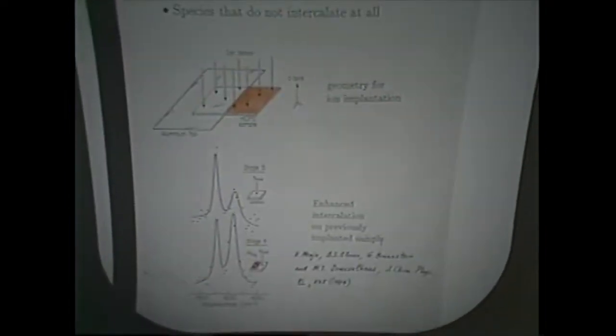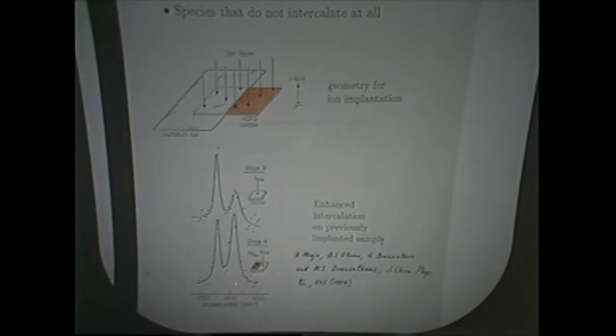So we have a control sample. Oh, well, I guess this is the whole thing. So we have the control sample here that was prepared at the same time, the same intercalation as this one, that half of it was implanted. And then we look with Raman spectroscopy on this side. We have a microprobe so we can look very close to the implanted region. And we do get an enhancement.